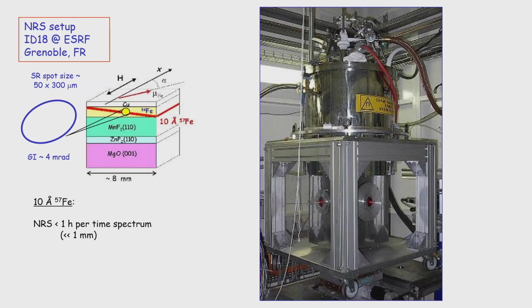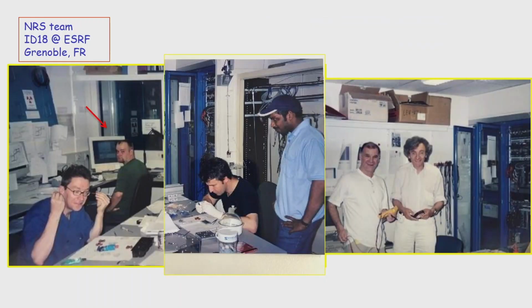Okay, and that means for a standard CEMS spectrum, you need 1 week, and in the synchrotron, we need, let's say, 1 hour for a spectrum, okay? In a very small region. And then from the spectrum, we can calculate the average orientation of the spins, and this is what we did. This is the team at that time. You can see this guy is sitting there, a little bit older, but he was doing his PhD at that time, and we shared the beam time with them. Okay, it was a very good beam time, nice time.